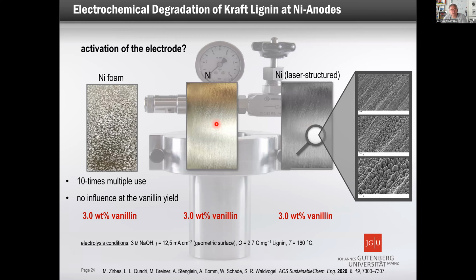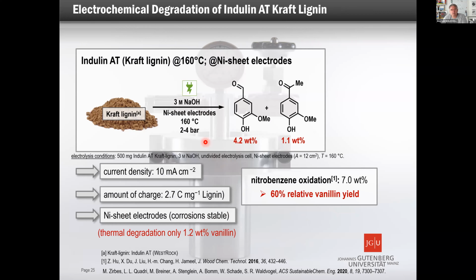Therefore, at that high temperature, you can work with simple planar systems. And then we play around with different lignin versions, and it turned out if you have specific lignins and you work with that, then you can go over 4%. And you see, we are all the time in the same range of the nitrobenzene oxidation. That seems to be quite stable.